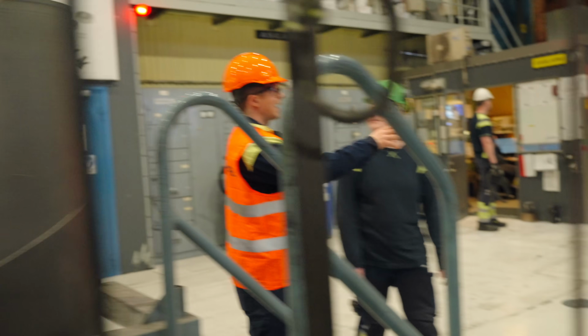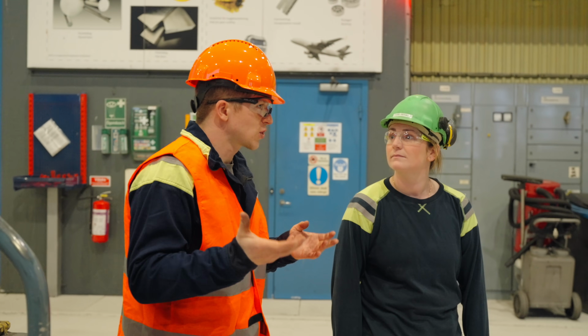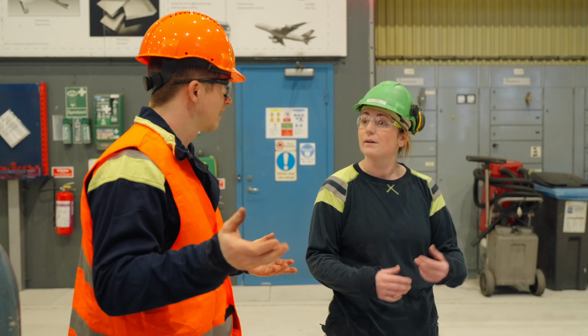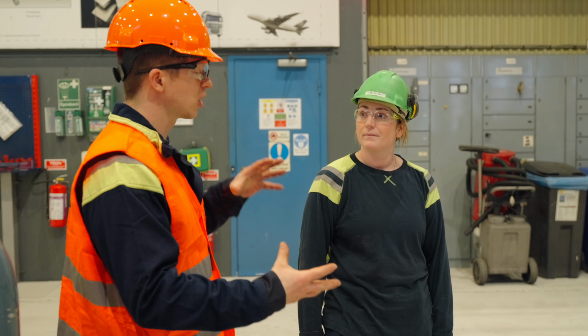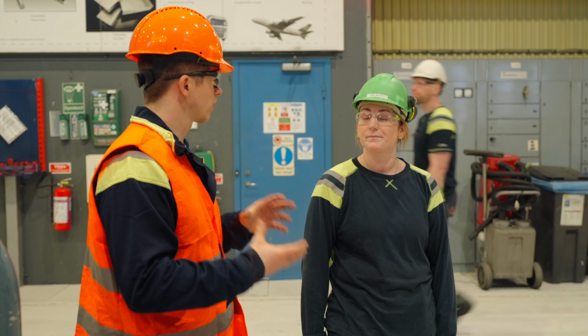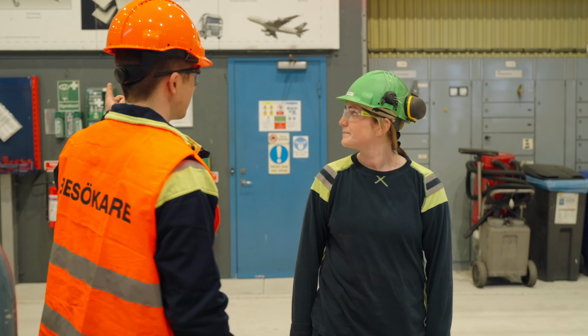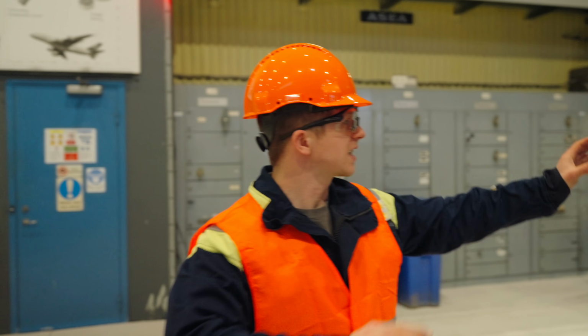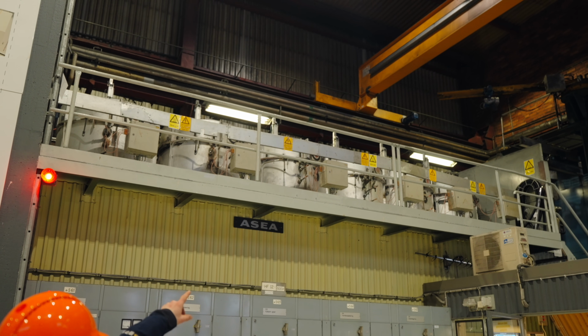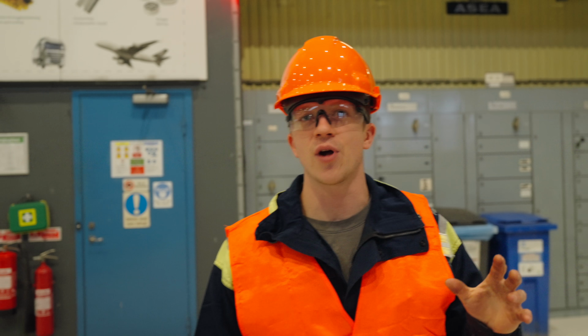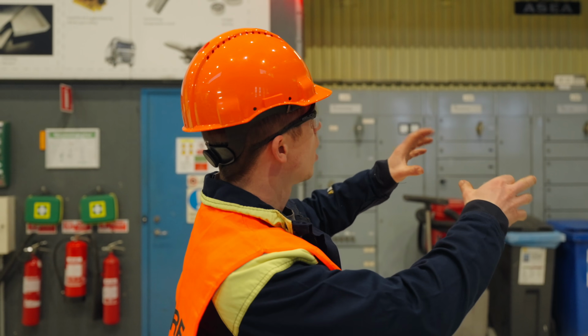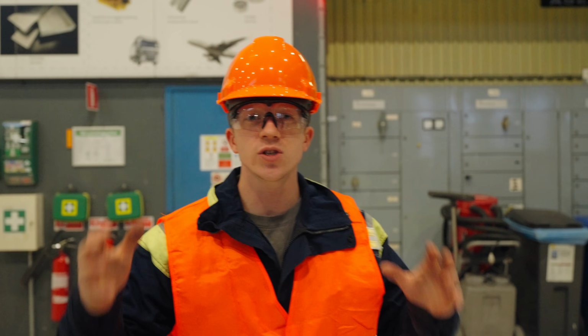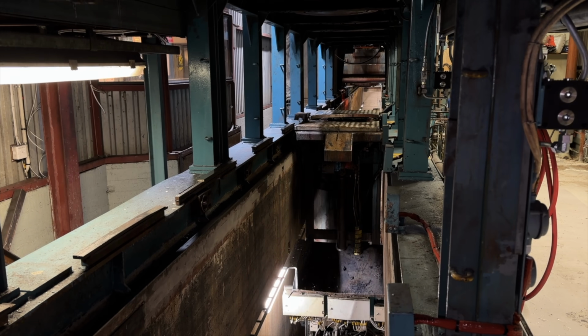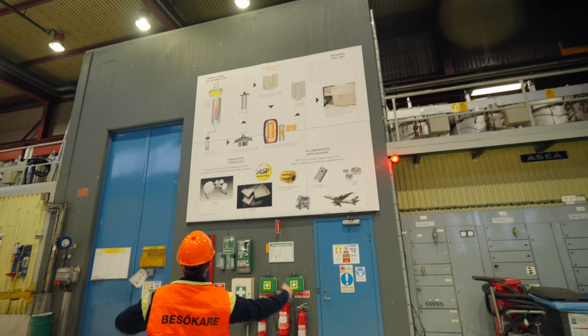And so they sit there, but it's not solid. It's just crushed powder. Yeah. The hot isostatic pressing is where it actually becomes a solid steel inside, and that's here. Yep. So from the cold isostatic pressing, they're then eventually taken into these furnaces over here. And this is the structure of the hot isostatic press. They're preheated over hours and hours, up to like 1,000 degrees Celsius, before, on train tracks, they're brought into this.